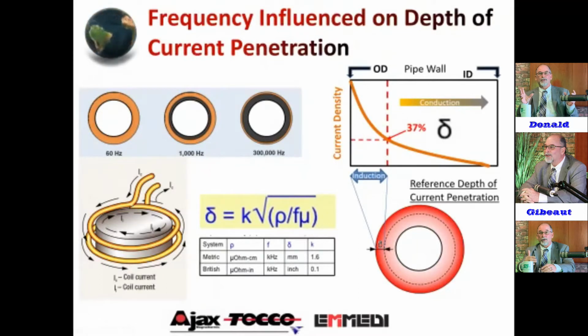I mean, because we want uniform delta T from the surface to the core. So conduction then plays a factor in the rest of the heating uniformity. But unlike a gas furnace, where we're just hitting the surface and having to conduct the whole way through the tube, we're inducing current at this reference depth of penetration. And we can pour the coals to it. We can put a lot of current in that area without overheating the surface, versus a furnace or just surface heat. You've got to be cautious not to overheat and cause grain growth in your metallurgical grain structure.